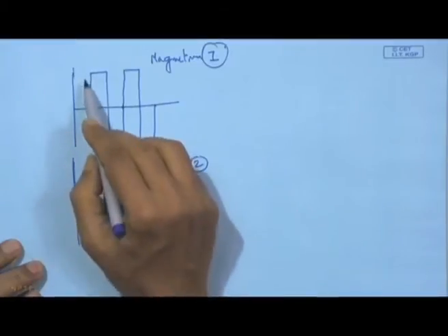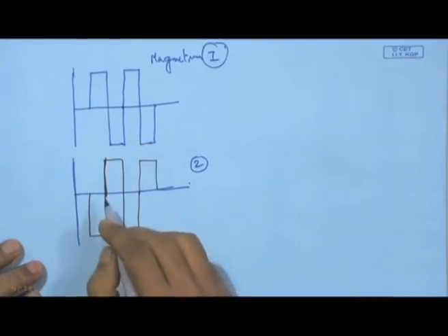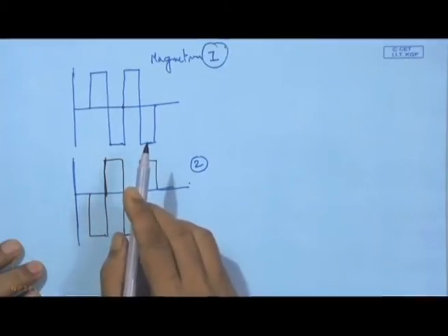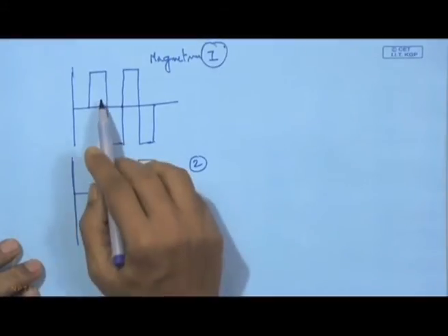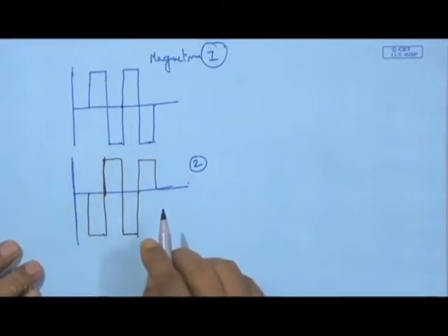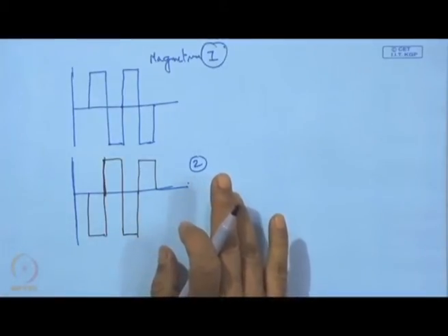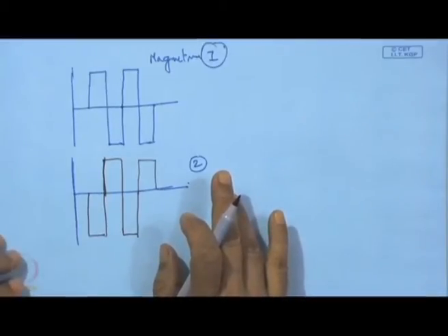When one is under positive polarization, the other one will be with negative polarization, and this way one power supply can be well utilized. So, one is active and the other is at that point not active, but their accumulated charges are neutralized and both are functional, made functional by the use of just one pulse generator.